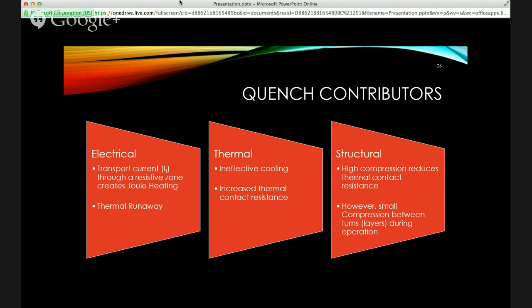However, when you have small compressions between your turns, it's kind of difficult to see now, but once I show you the picture, then you'll have an aha moment. But when you have ineffective compression, it can actually create delamination, or it can create cracking or some type of movement between your different layers.